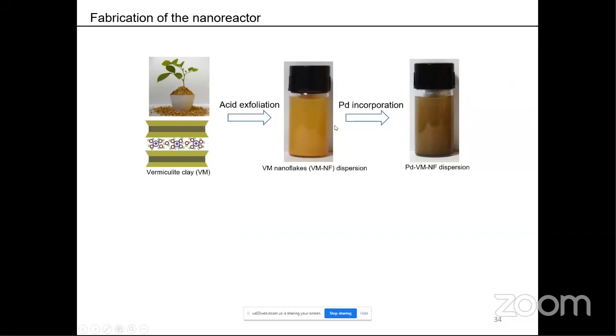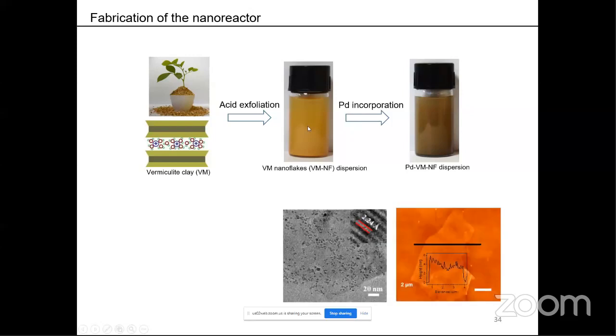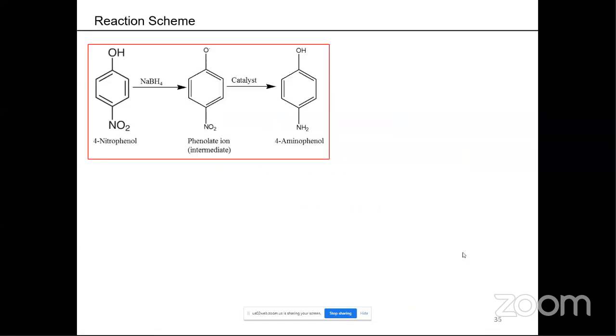We have taken some vermiculite clay, dispersed it into water and mixed it with palladium nanoparticles. These are the nanoparticles you can clearly see from the EM image. These are some AFM characterizations to show that these materials are actually 2D materials. Now we have taken a very simple reaction to prove this concept. We have taken nitrophenol molecules and put sodium borohydride to reduce it to aminophenol. The moment we put sodium borohydride, it gives us a phenolate ion, and in the presence of catalyst and sodium borohydride, this phenolate ion transforms into aminophenol.